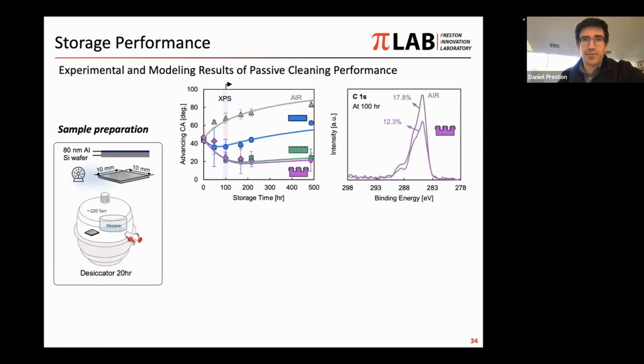We also looked at the performance in terms of taking samples that may initially already be contaminated and using the container to clean them, to remove contaminants, and that worked as well. So in this case, we have the same aluminum wafer or aluminum coated silicon wafer. In this case, we put it in a desiccator for 20 hours with hexane. So we tried to make a well-controlled level of contamination on the surface. That's what gave us this initial contact angle of just over 40 degrees. And then we looked at the evolution over time.